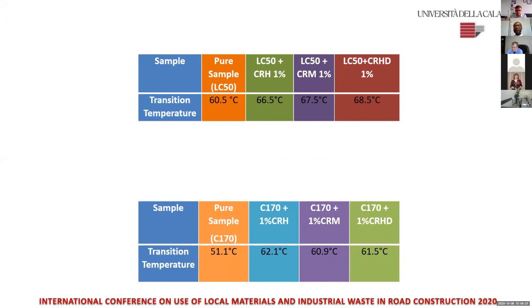Now, we calculated the differences in the transition points of the pure sample and the modified sample. The pure sample of LC50, the hard bitumen with the 50-70 penetration grade, has a transition temperature of 60 degrees, while the one with the additive has 66.5, which increased the transition point, a good thing. It improved the rheological characteristics. For another variant we have 67.5 degrees, and here 68.5 degrees, which is a very, very good result.